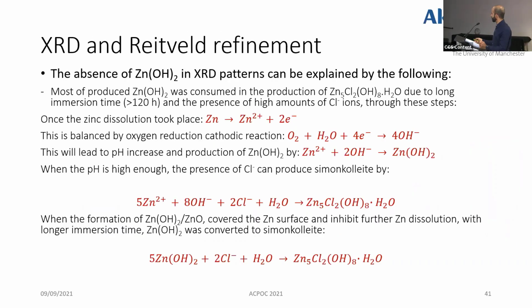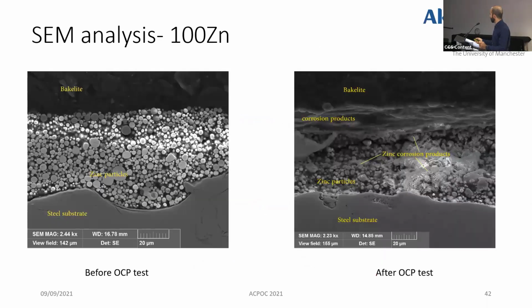And this is because of the presence of high amounts of chloride in the NaCl solution with hydroxide ions from the cathodic reaction. So this all produces the simonkolleite, which is the main corrosion product, and also over longer time, the zinc hydroxide that's formed at the beginning is also converted to simonkolleite in the presence of a high amount of chloride in the solution. The SEM analysis for each coating before and after the test allows us to see the morphology inside the coatings after the test.